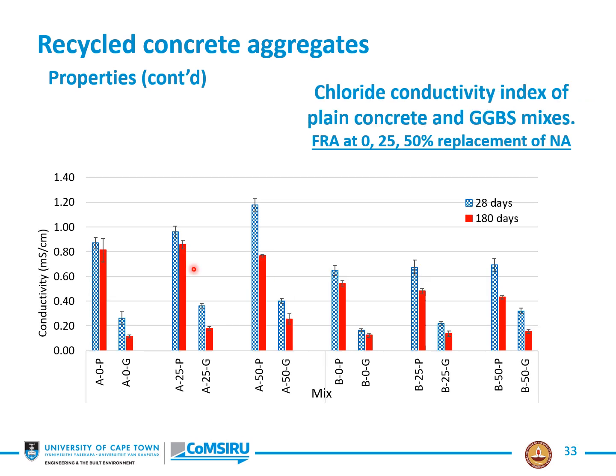If we look at the chloride conductivity index of plain and GGBS or slag mixes, the same picture emerges. The slags, of course, have very substantial effects on bringing down the chloride conductivity, as we know. But the recycling of the aggregate here, fine recycled aggregates in this case, also has no major detrimental effect, even up to about 50%. So it's possible to do this. This is good, and these are excellent.